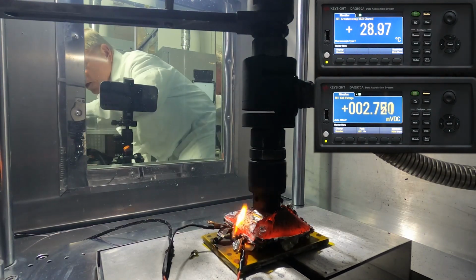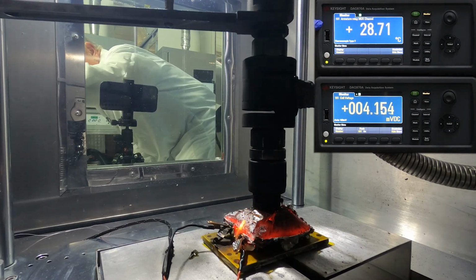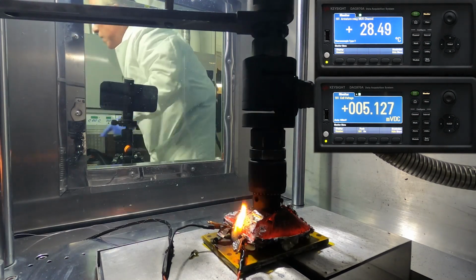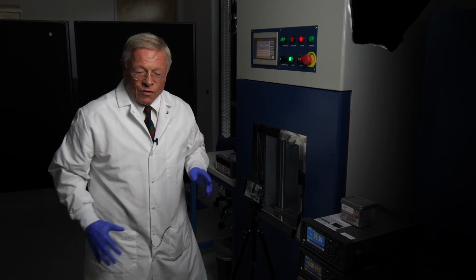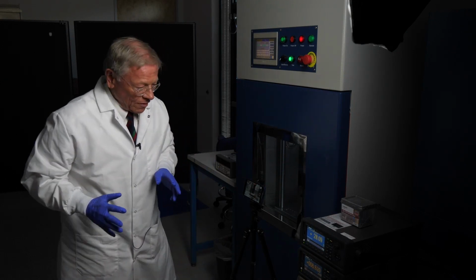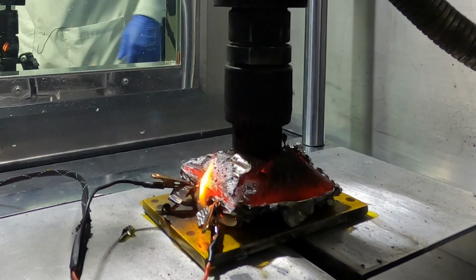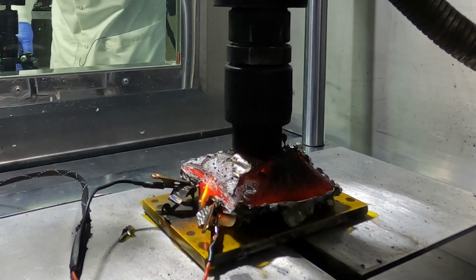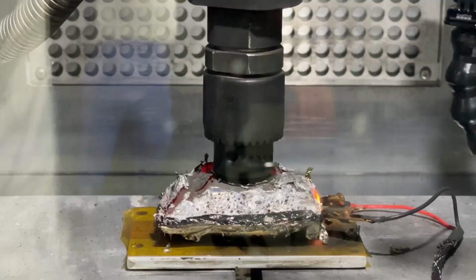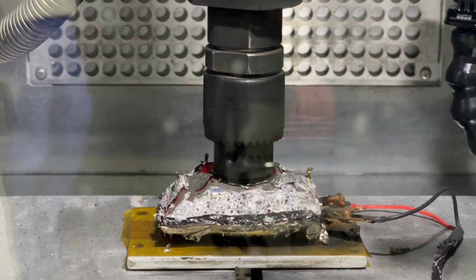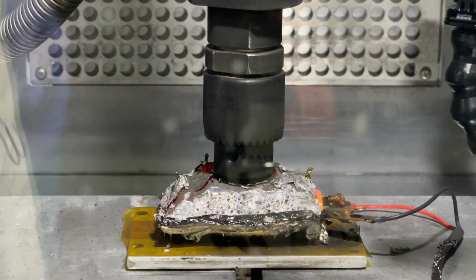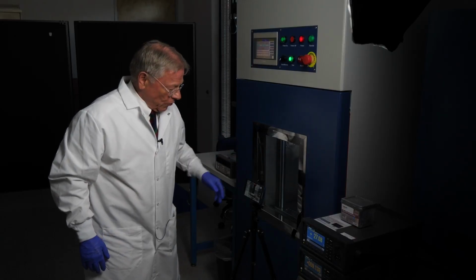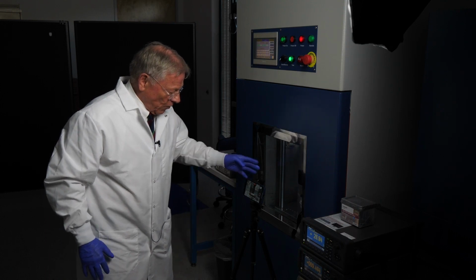and our temperature, I guarantee our temperature is not 28 degrees. The reason is that the thermocouple evaporated at 400 degrees centigrade, so this is like over 1,000. You can see, stuff splattered all over. So this is a classical fire that happens when you crush or penetrate a lithium-ion battery, and this is what you're trying to avoid.